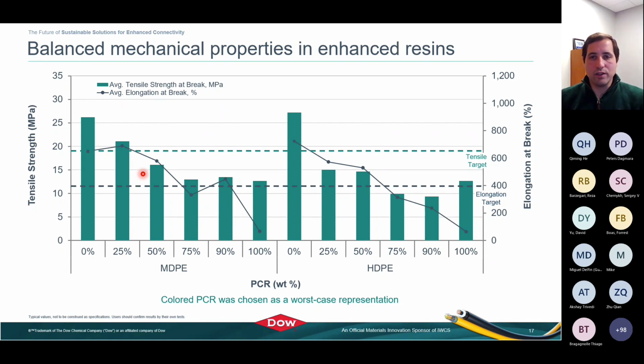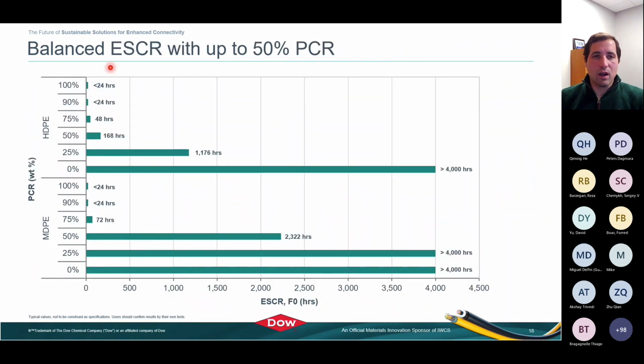And again, similar trend, you see the drop off as you increase the amount of recycled content. Similarly with ESCR, depending on the applications or targets that you would have, there is a range of performance that you can get, but really I would say in that 25 to 50% range. With these higher performance resins, you can have relatively good stress crack resistance, as you can see, upwards of